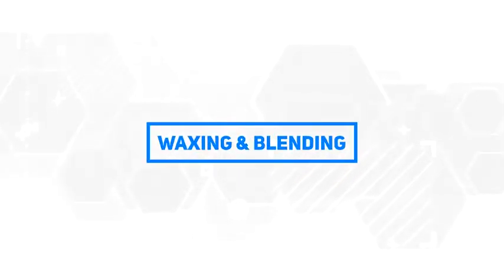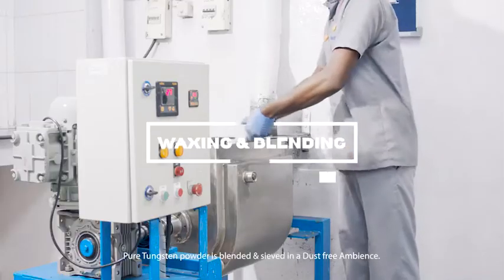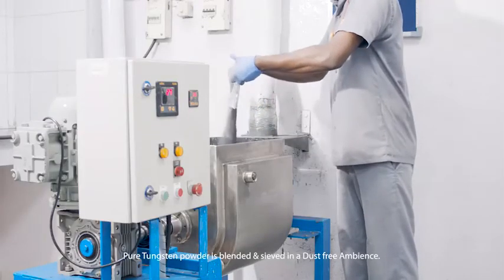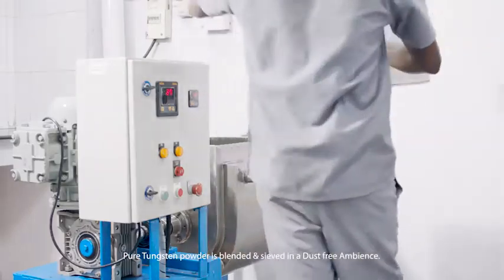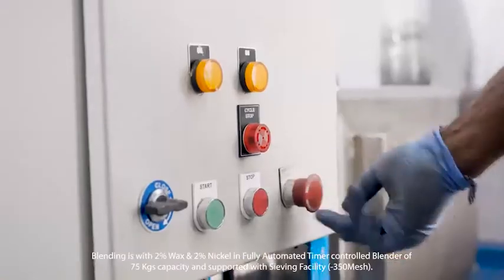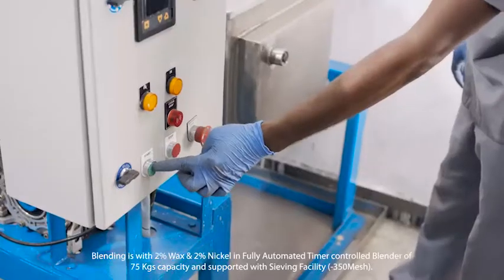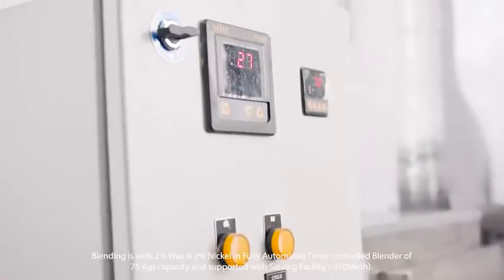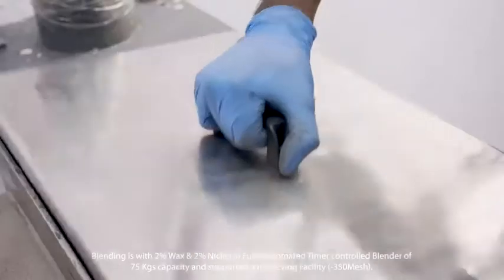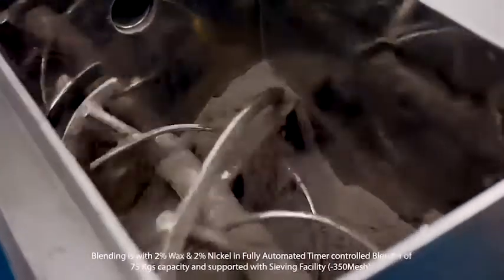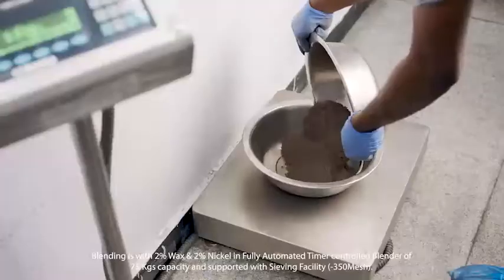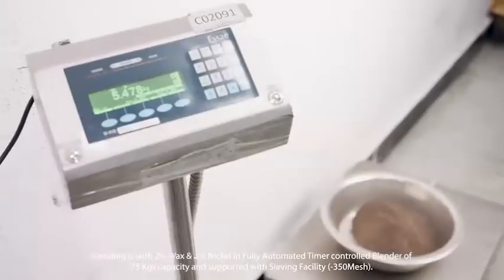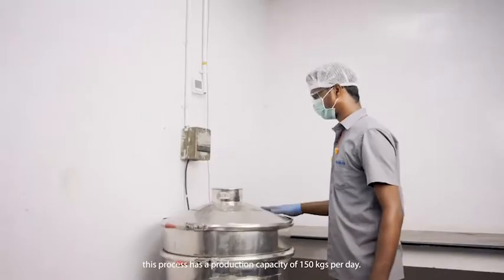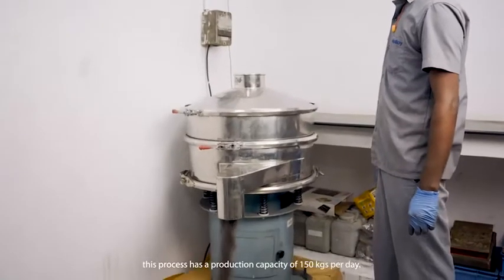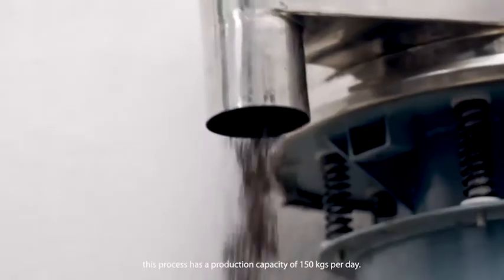Waxing and blending. Pure tungsten powder is blended and sieved in a dust-free ambience. Blending is with 2% wax and 2% nickel in a fully automated timer-controlled blender of 75 kg capacity and supported with sieving facility, minus 350 mesh. This process has a production capacity of 150 kg per day.